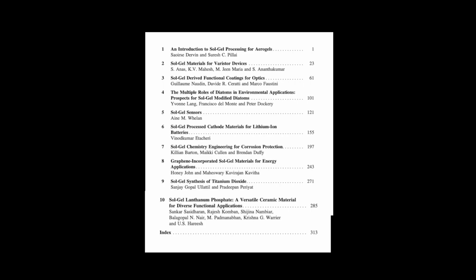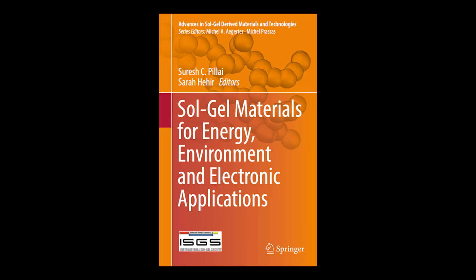By creating these hybrid inorganic networks, for instance, by carefully varying the Si/Ti ratio in a mixed oxide film during the sol-gel process, you can continuously tailor the refractive index. The sources note you can reliably hit pretty much any point between 1.45 and 2.27. That dynamic range gives you tremendous design flexibility.